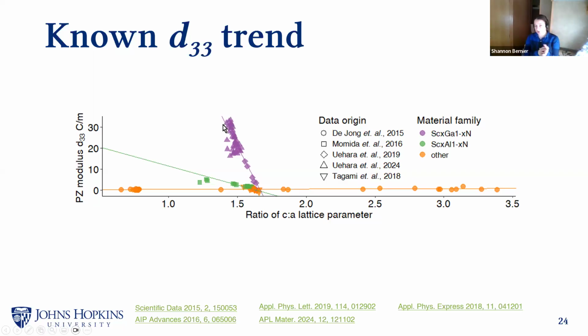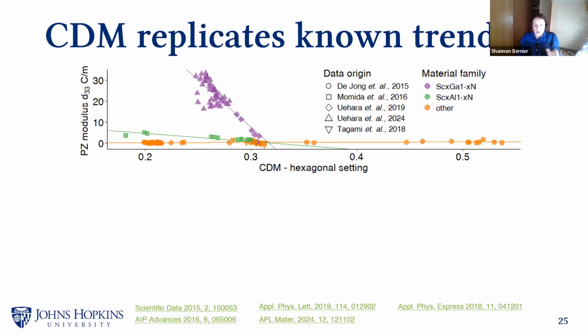So we were curious what the cubic deviation metric would do when we applied it to this situation, because as the C to A lattice parameter ratio decreases, you're basically coming up with a quote unquote more cubic unit cell because the side lengths are becoming more similar. It never becomes cubic because it is still hexagonal, but it does become quote unquote more cubic. And so this is something that someone in our field would call a pseudo-cubic transition. And the CDM does in fact replicate this trend.